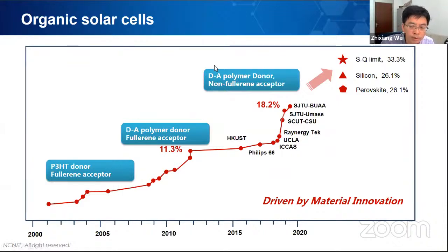And for organic solar cells, at the beginning, their efficiency was quite low. But in the last 10 years, especially in the last 2 years, driven by material innovation, you can see their certified efficiency actually increased quite fast. Now it's approaching 18 or 19. Yeah, this is already not far from traditional solar cells. For example, single crystal silicon, the efficiency is 26. The Shockley-Queisser limit for single junction solar cells is 30%.